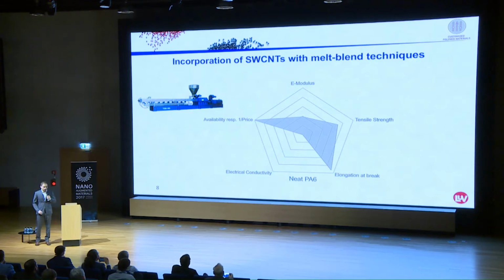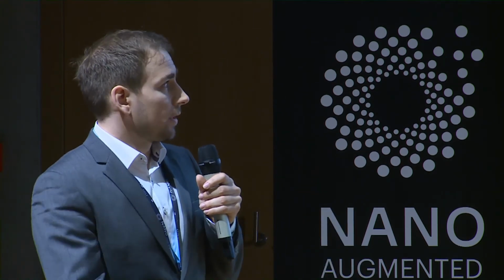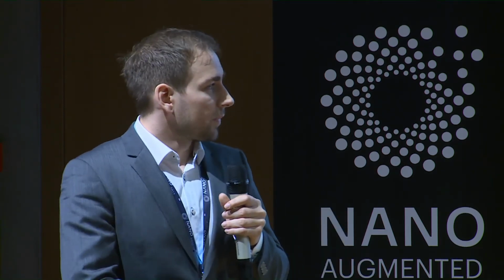And here is what we are doing. So the state of the art for compounding today is to use an extruder to melt the polymer material and mix it with the filler. In this case here, I used an extruder and carbon nanotubes to change the property profile of PA6.